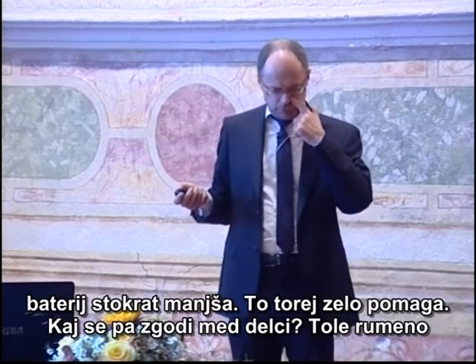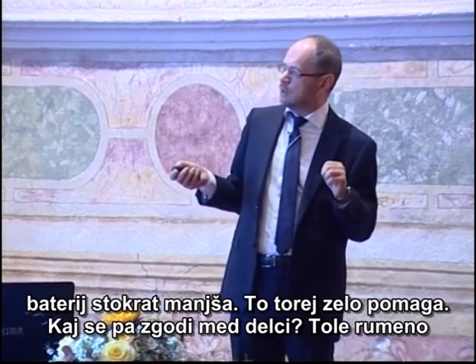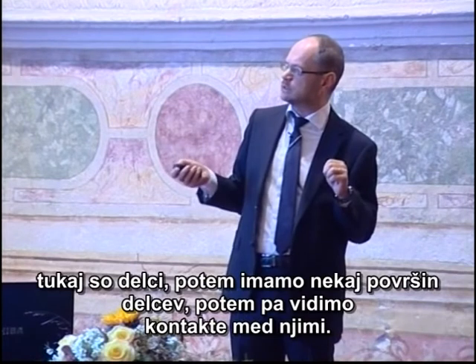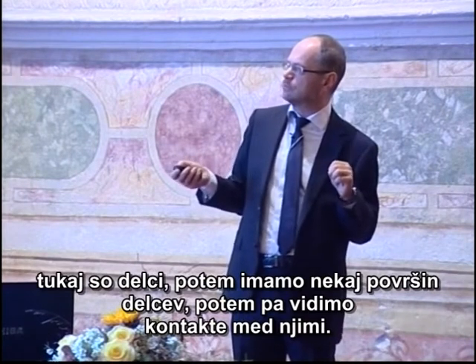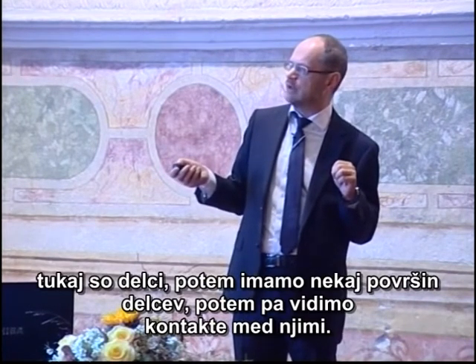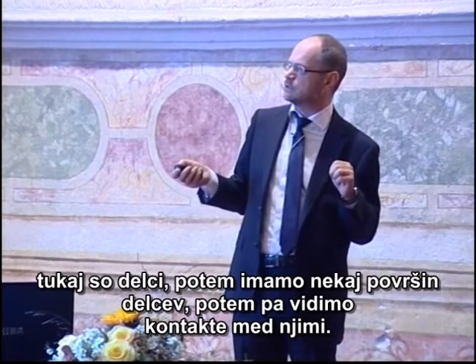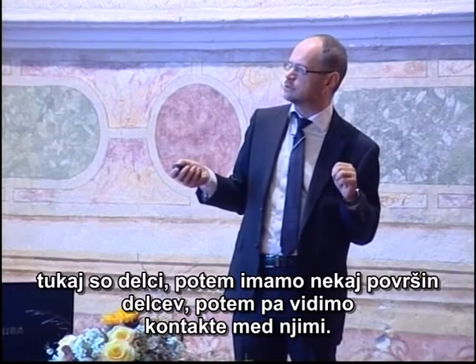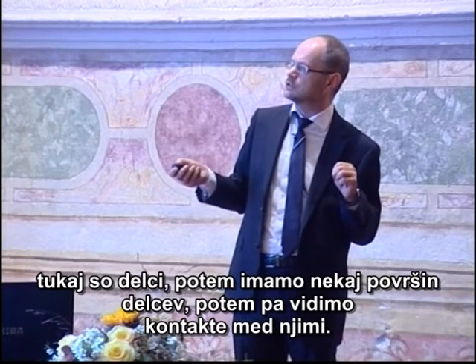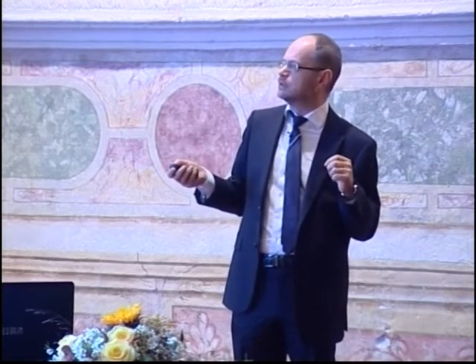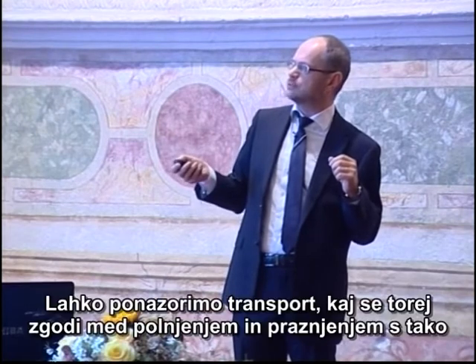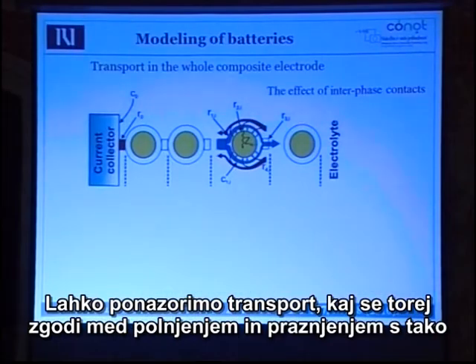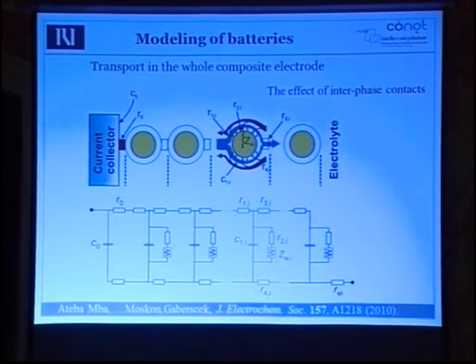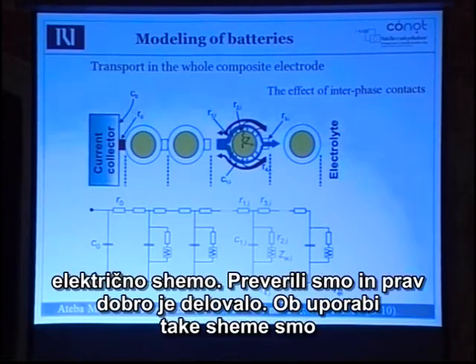Then another point of view is, what happens in between particles? Let's say that these yellow balls here are particles, then we have some surfaces of these particles, and we have these contacts, like these squares, rectangles actually. Contacts between particles. This is a scheme. So we can model transport, what happens during charge and discharge. We can use electric schemes like this. This has been checked. It works quite well.